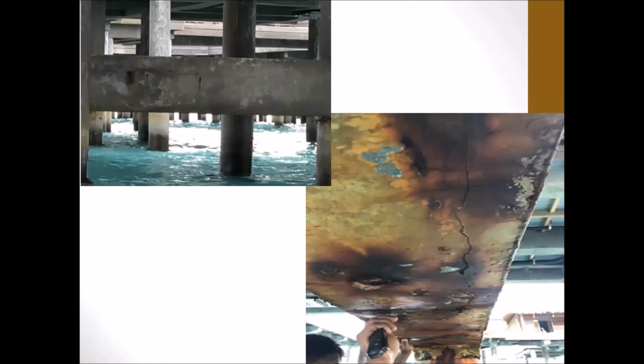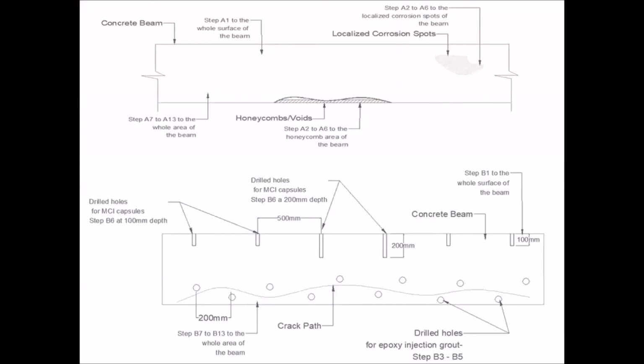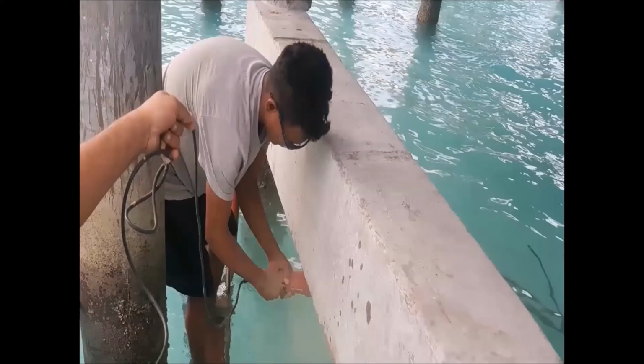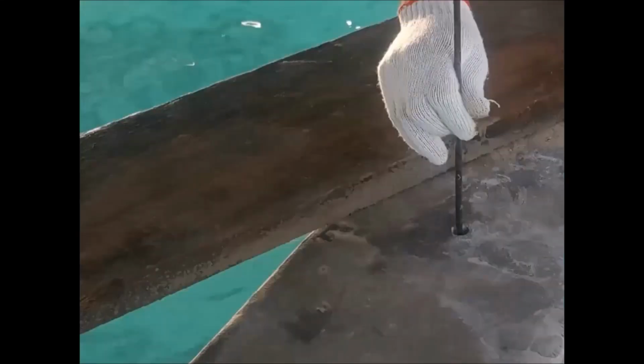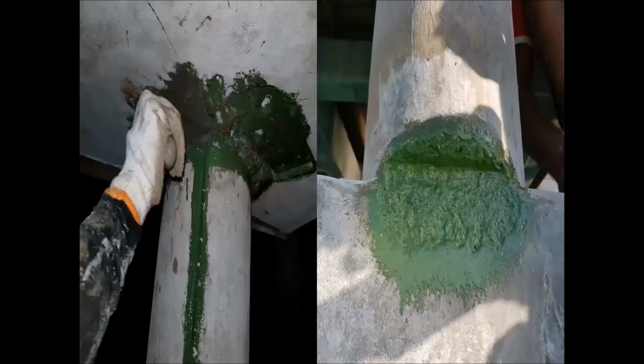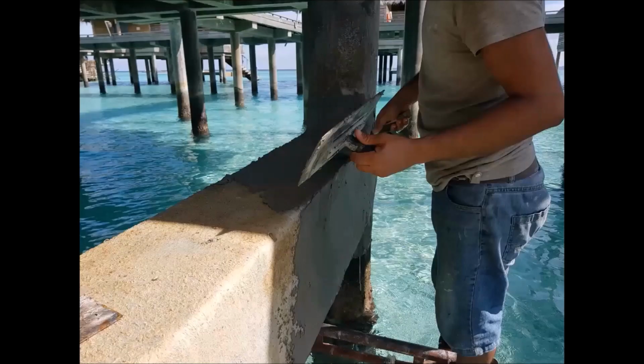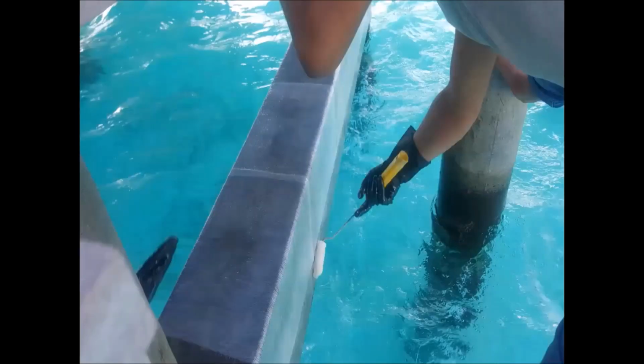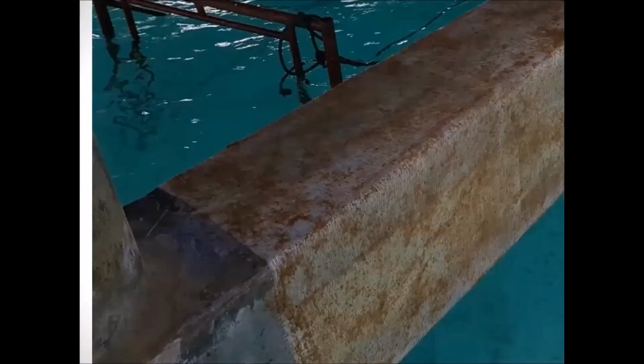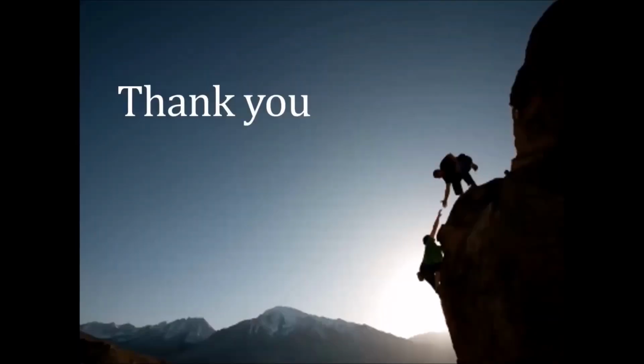Marine structure, this is not in Sri Lanka. These are the honeycomb areas, and you can see in the bottom picture the migratory corrosion inhibitor capsules we can use. Grinding, inserting migratory corrosion inhibitor capsules, epoxy bonding and repair, use of glass fiber for durability, and sandblasting. And thank you very much.